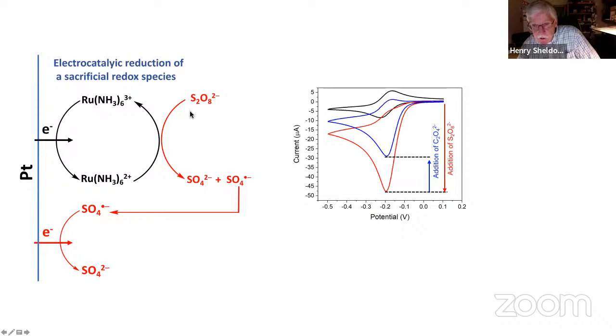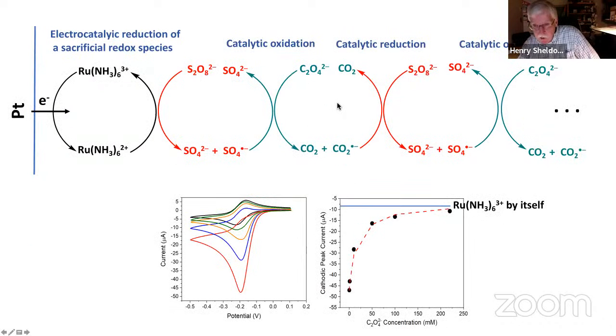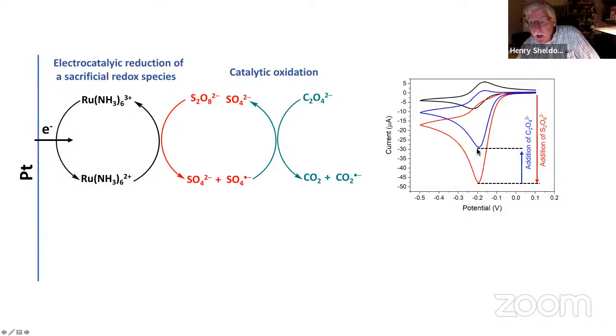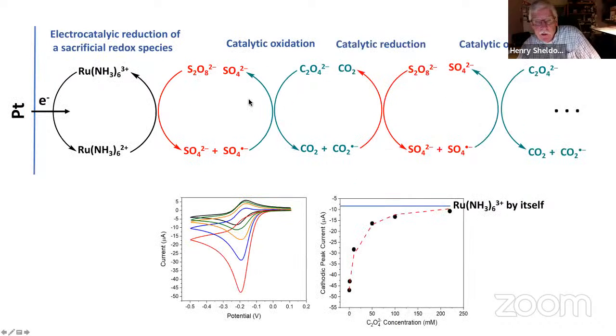And then you add oxalate. Oops. You add oxalate, and what happens is the current goes down. And the reason it goes down is because this persulfate is not making it back to the surface, but it's being used to oxidize oxalate. And that's a chemical reaction. You can't detect that at the electrode. That's invisible to the electrode or the electrochemical signal. Okay. And you keep adding more oxalate. And you get this reaction to go.